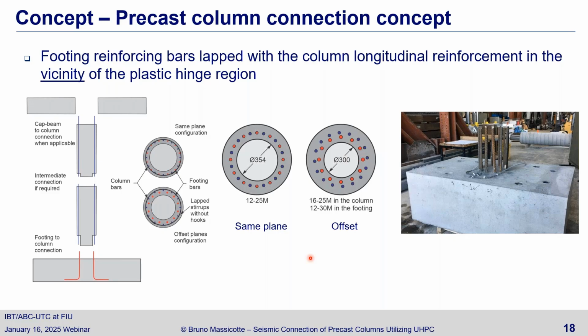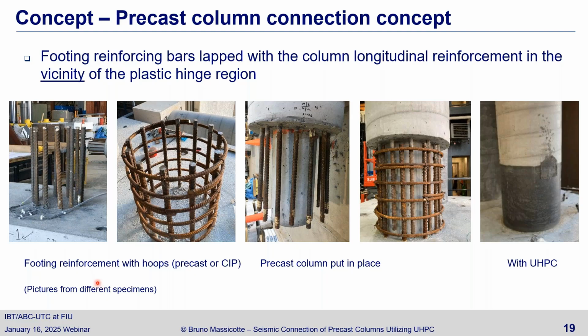As mentioned here, all the pictures are not coming from the same element, so you can see that the bars are not exactly the same from one picture to the other. But you have the bars coming out of the footing here. Then you put some hoops here, and you have your precast element with the longitudinal bars, and then you just put the two elements together and pour UHPC, and that's it. It's no more difficult than that. And one good thing is that with UHPC, since you can reach 400 MPa or 60 ksi with a lap splice of about 8 bar diameter, you don't need to use hooks at the end of your bars. So you can have much easier details to put in place when you lap bars in UHPC, whatever kind of bar you have.